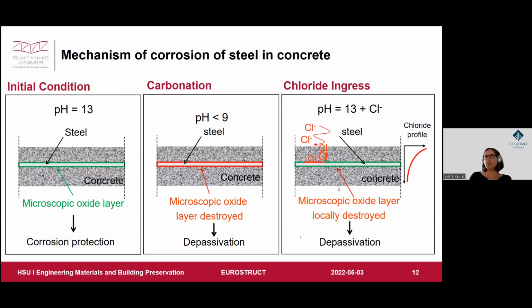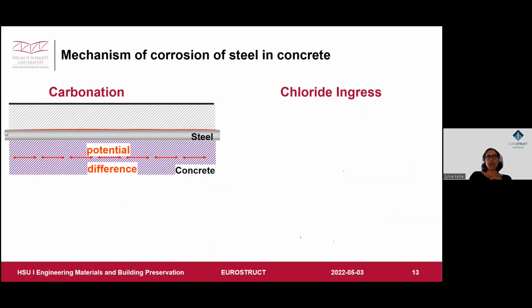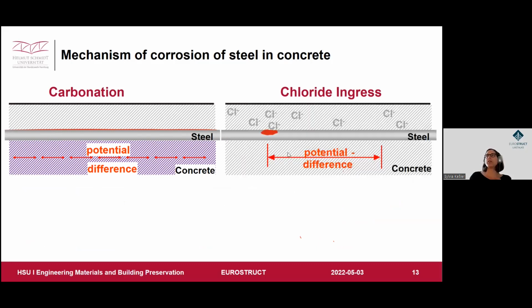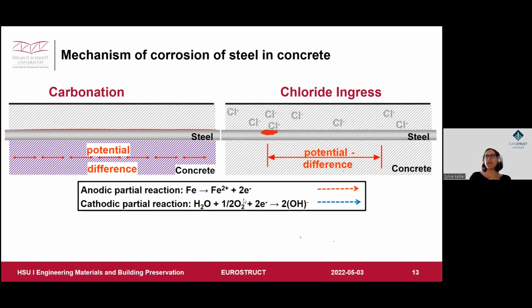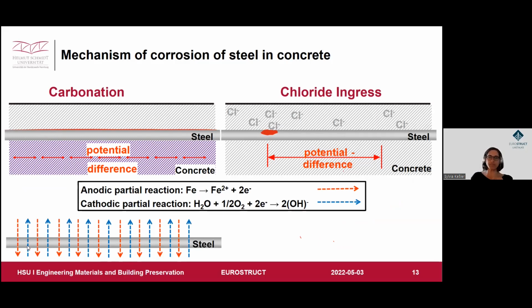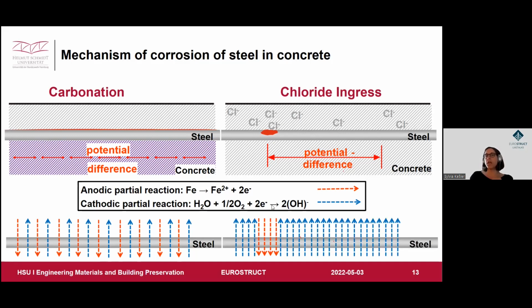But what is really the difference between both mechanisms, the carbonation-induced corrosion or the chloride-induced corrosion? Normally, with carbonation we have a very homogeneously distributed depassivation of the steel, so very uniform corrosion, whereas in chloride ingress, we have it very locally, as I mentioned before. And this means that the anodic partial reaction and the cathodic partial reaction will take place in typically different locations. Here, it's distributed equally over the whole reinforcement, whereas for chloride-induced corrosion, we have a concentration of the anodic partial reaction leading to the typical pit, which leads to other complications for the structural engineering. And here I promise this is the last chemical equation you will see today.